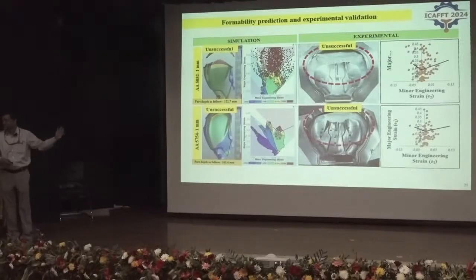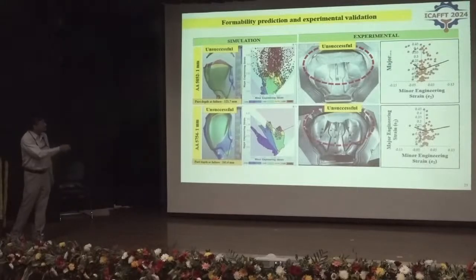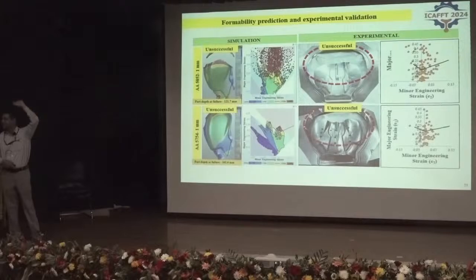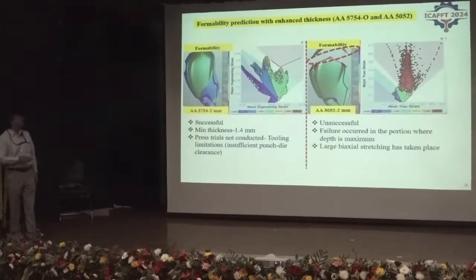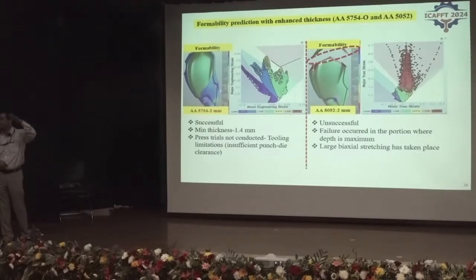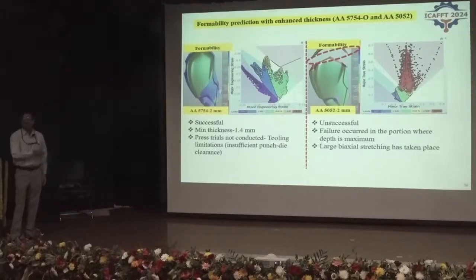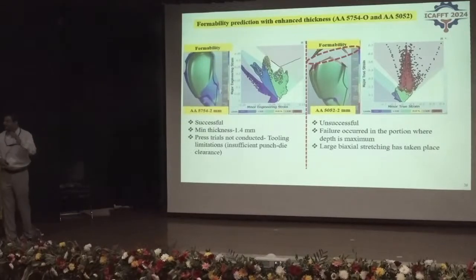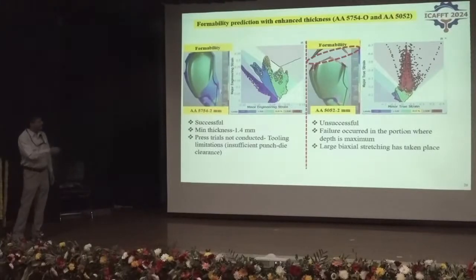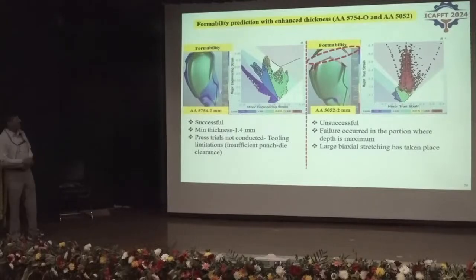This was anyway expected because the sheet thickness is equal to steel sheet thickness. And experimentally measured strains also, you can see they have far exceeded the forming limit curve, and this was what was expected. So then we predicted formability of these two alloys for fuel tank manufacturing by enhancing the sheet thickness. So we went up to 2 mm, and for 5754 we found that if the sheet thickness can be increased to 2 mm, it can be successfully formed, and the minimum thickness would be 1.4 mm. I know the aluminum alloys are costlier, and if you increase the sheet thickness, it would be even costlier. But the thing is that the weight of the component will still be lower even if it is 2 mm. But in case of 5052, even at 2 mm, the predictions were unsuccessful. I mean, unsuccessful forming.